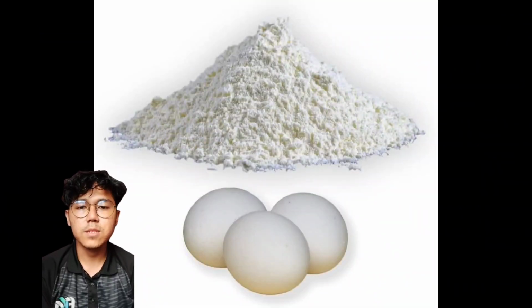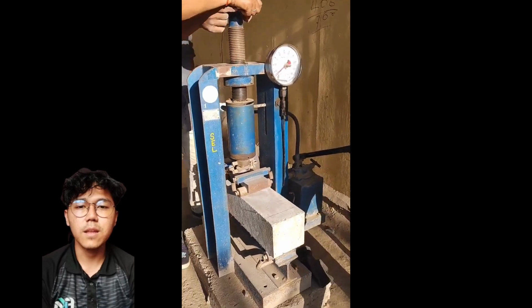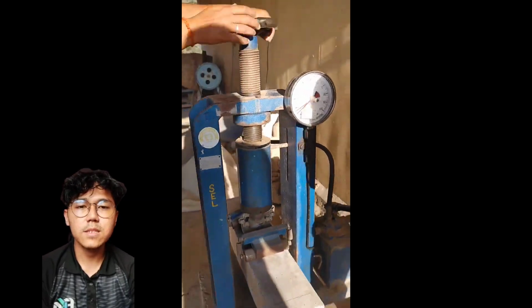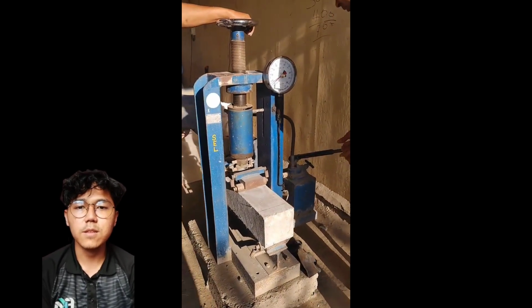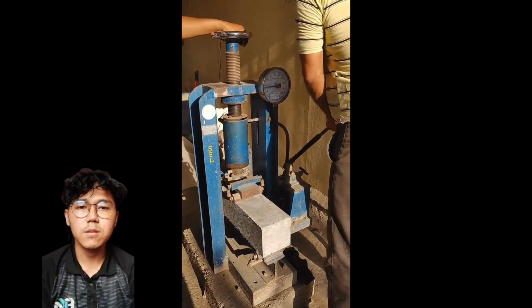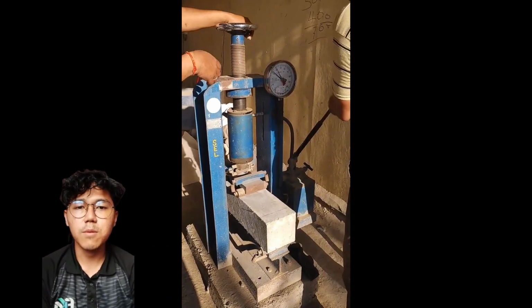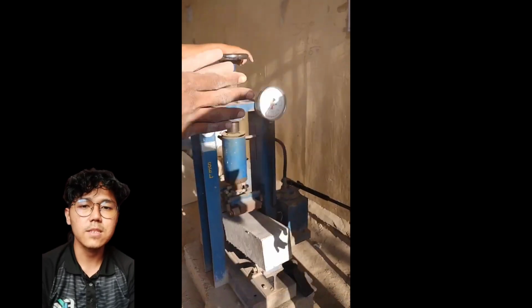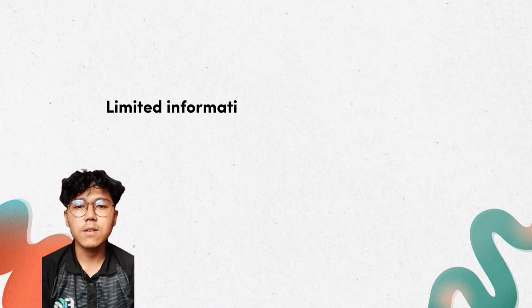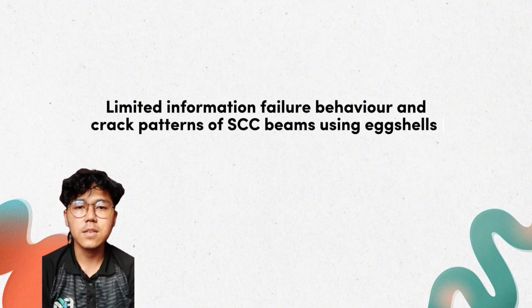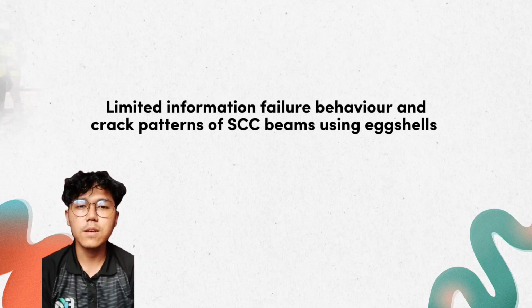Eggshells as partial substitutes for sand or cement have shown positive results in maintaining or enhancing concrete strength. Flexural strength in beams has been found to increase with increasing compressive strength of concrete, while extensive research has been conducted on reinforced concrete beams with various additives or waste materials. There is limited information on the failure behavior and crack patterns of SCC beams that include eggshells as a component in flexural tests, leaving this area open for further investigation.